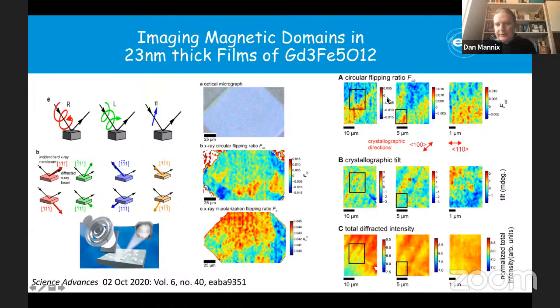The third thing that I want to highlight is, again, looking at the magnetization data, the magnetic domains, zooming in on different features. And I want to compare that with the crystallographic information that we can get. So we can get two types of crystallographic information. The first is the total intensity, the sum of left and right, so this is just the atomic scattering. And you start to see some features here which go along these kind of directions, and that's going along the 100 direction.